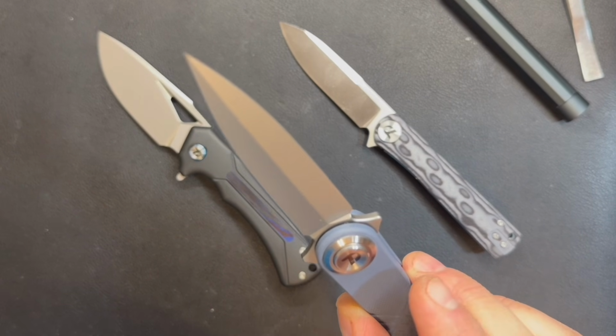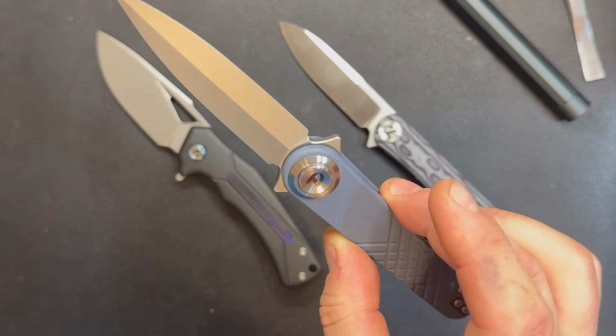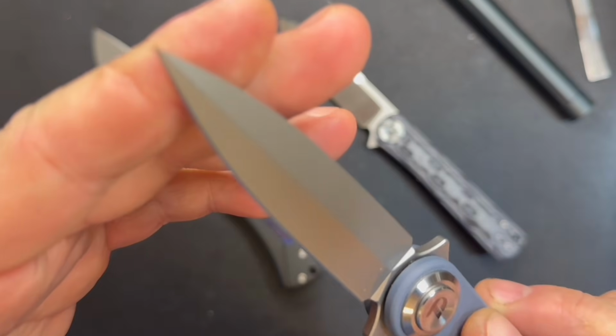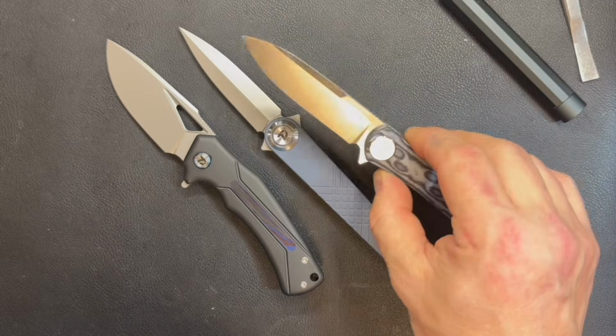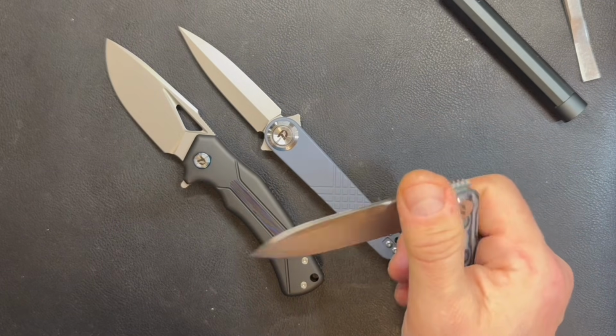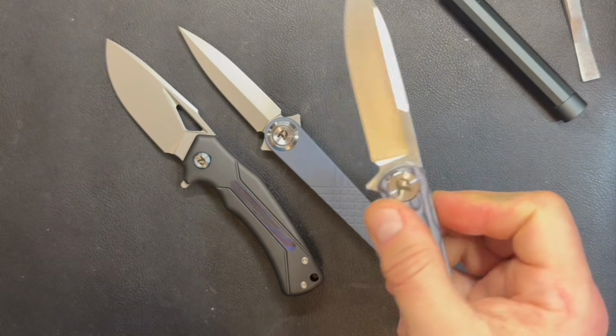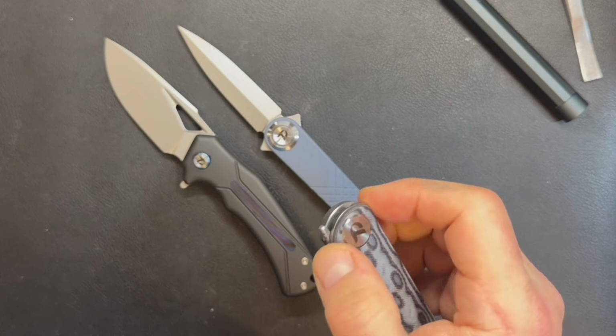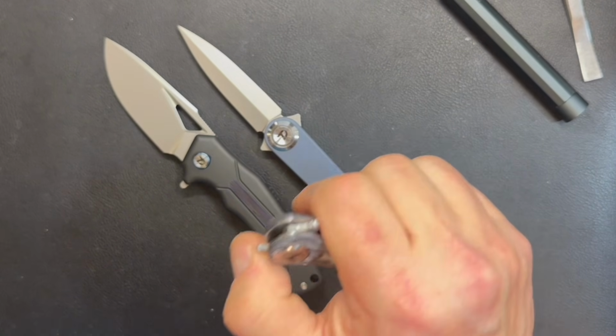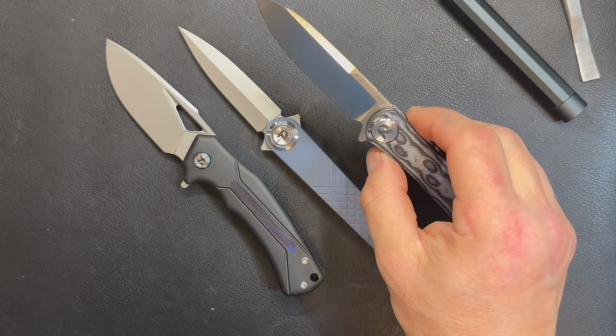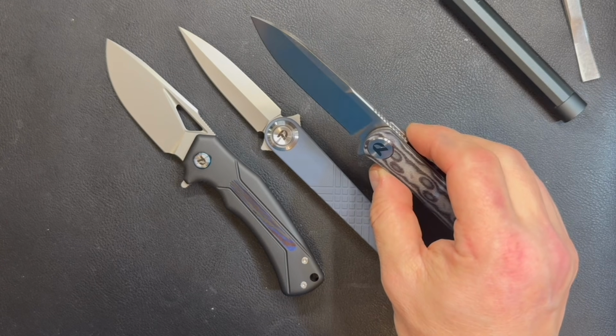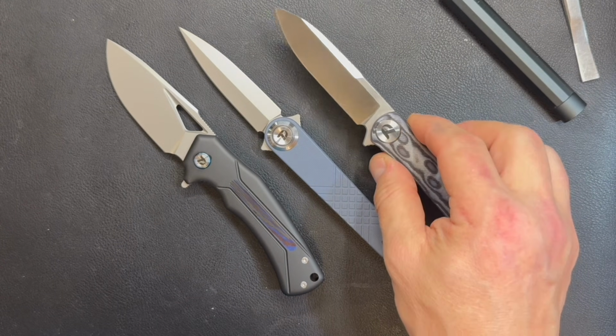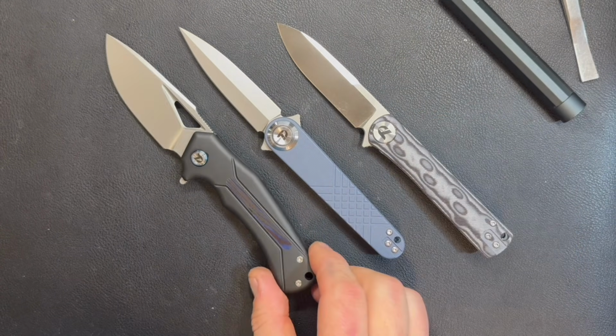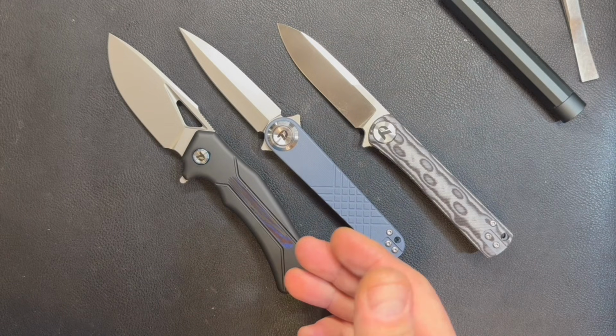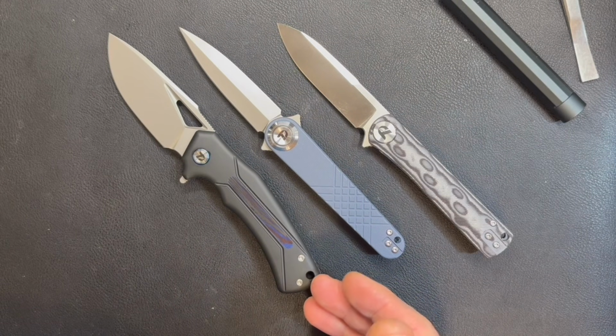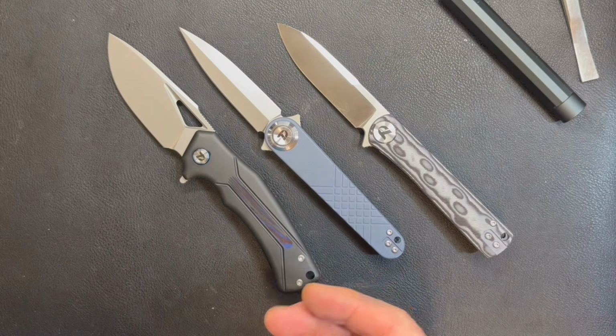The tip I can regrind, but that lock face will wear out as if it was made out of cast iron. That liner lock knife is really well built, but that excessive hardness on the blade worries me quite a bit. Because 65 HRC is the highest hardness you can achieve by austenitizing D2 steel, and then if you forget to temper, it will stay at that hardness. So lack of tempering is a major concern. I suspect this blade will be as brittle as glass.